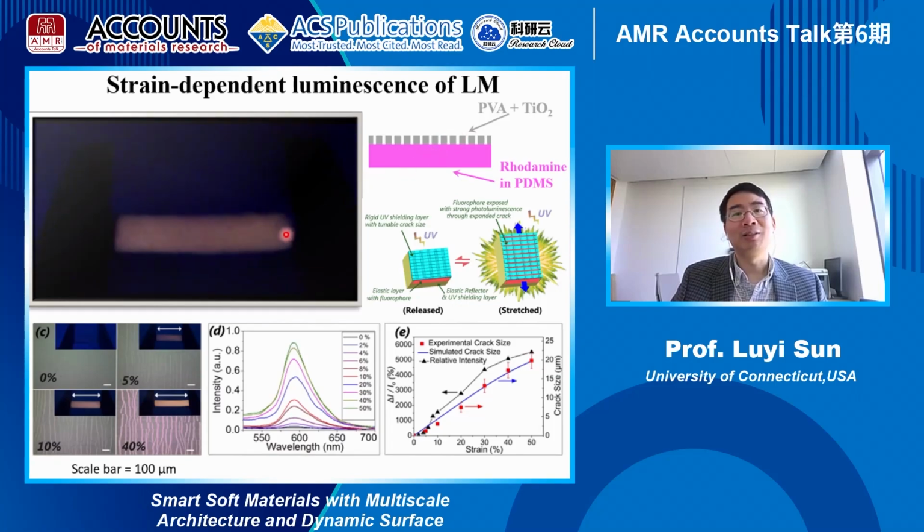And this is a very simple device, as you can tell. Very, very simple, but on the other end, it's highly sensitive. It only requires 3-4% of strain to generate the color. But the biggest advantage for this design is that now we can generate color at will, whatever color you want: yellow, green, orange, blue. You can just mix the pigments into the PDMS matrix, and then you can generate any color, and that is very versatile for real applications.